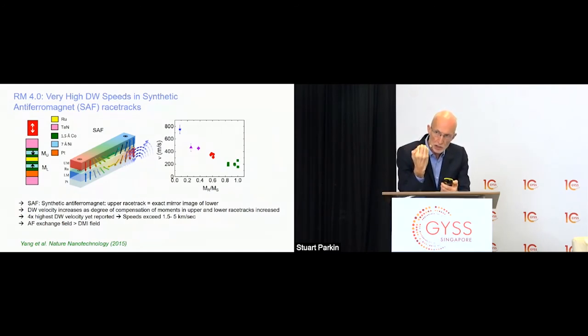The efficiency of the motion, the velocity of these domain walls under the same current pulse intensity, would be 5 times larger. And this led us to show that we could move domain walls in these systems at speeds exceeding 1 kilometer per second. And this leads to the possibility of creating devices that can operate on 100 picosecond timescales, which is faster than any conventional memory technology today. So this is very exciting.